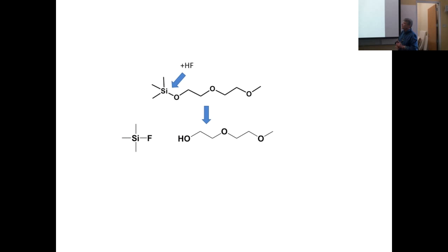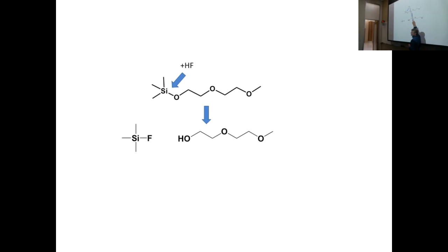But as I'll show you later, this is what's called an autocatalytic reaction, meaning that the HF produced by the reaction with water, so we have this PF6, it produces PF5, PF5 reacts with water, that produces HF. HF degrades the compound. The products of this are themselves electrochemically active and unstable. So you get this kind of snowball effect that once you begin to degrade a little bit, the whole thing just rapidly begins to totally tank. Okay?